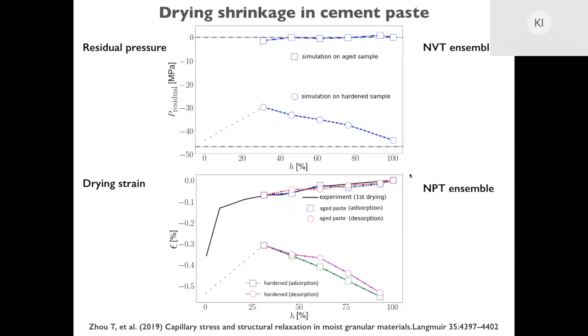You can see that we have a very interesting and non-monotonic behavior with the relative humidity. And what the results of the simulations show us is that if we cure cement with relative humidity between 30–40%, that is where we get the least shrinkage, and at the same time the eigenstresses relax the best. So in a way, what people have always been doing, covering cement with a thin layer of water and plastic to avoid evaporation, is also confirmed by simulations: even at the nanoscale, this humidity is preventing the material from having extreme volume changes.